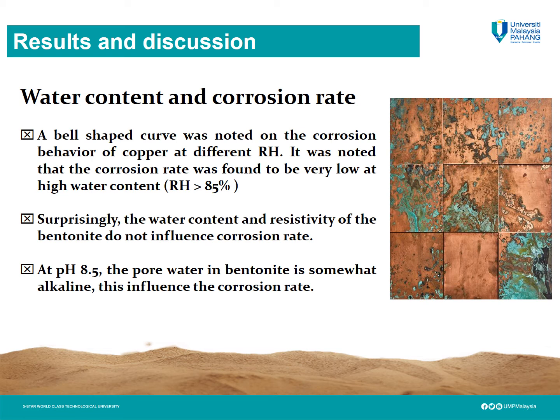Surprisingly, the water content and resistivity of the bentonite do not influence the corrosion rate as explained in the literature. Higher water content and lower resistivity usually will cause corrosion to occur on copper electrodes. The bentonite also has a pore water pH of about 8.5, and the pore water in bentonite is somewhat alkaline, and this influences the corrosion rate, which caused the corrosion to go very slow.